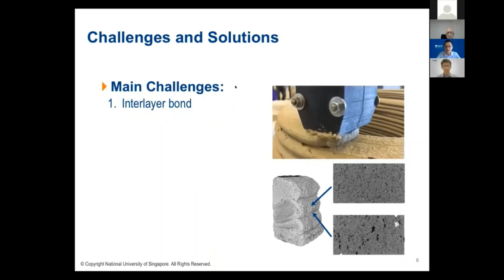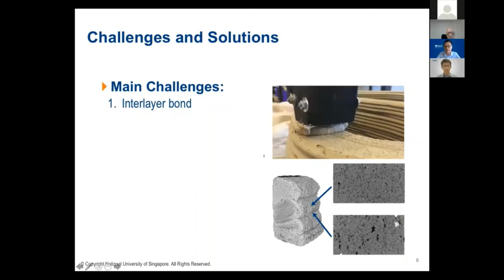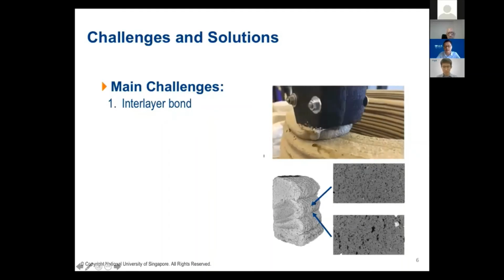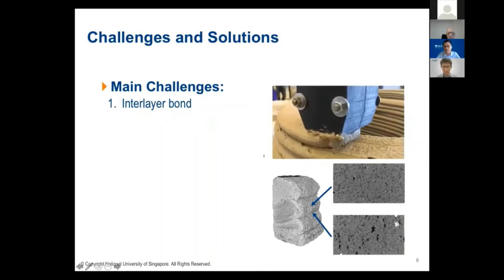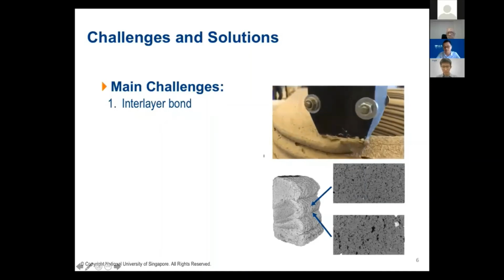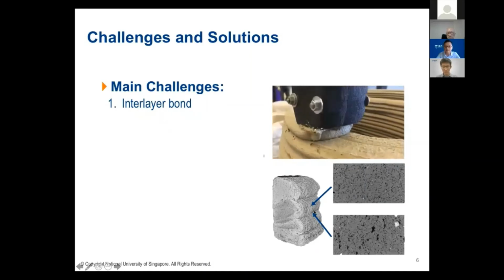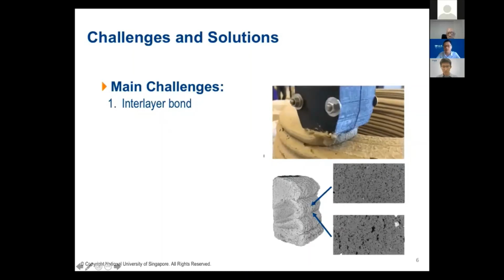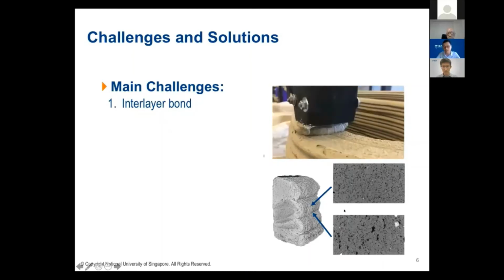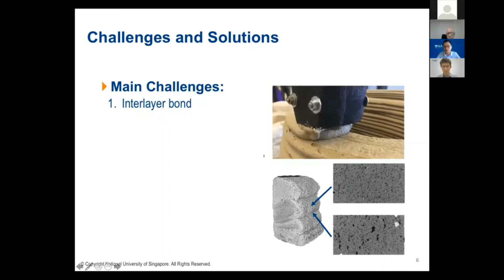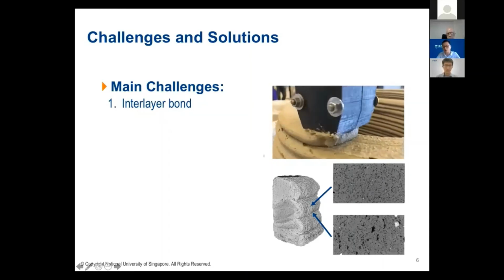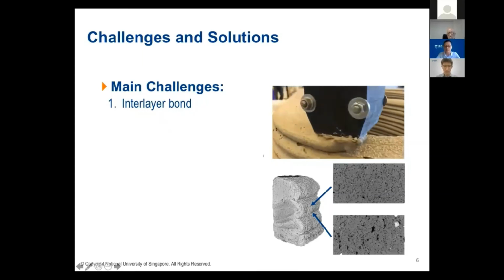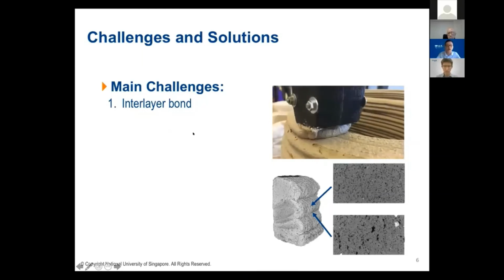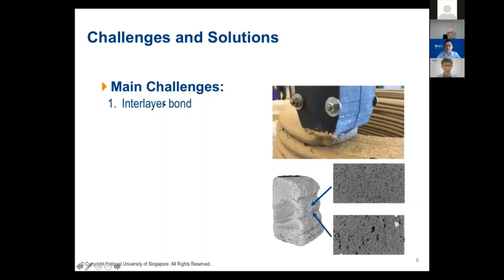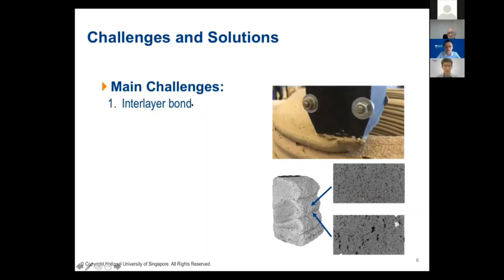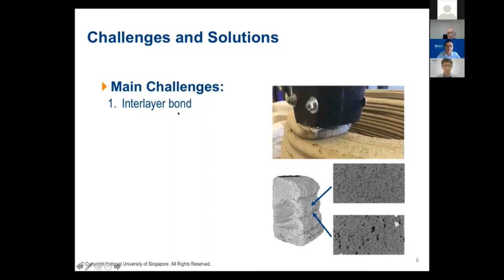The photo at the bottom is the CT scanning done by my student, and you can see the difference. This is the porosity, the microstructures at the interlayer at the bottom here, and the microstructure in the filament. So it's very obvious to note the interlayer has more porosity, and the pore size is much bigger than the filament. So the interlayer bond is something that can control the concrete quality, mechanical strength, and then the durability.